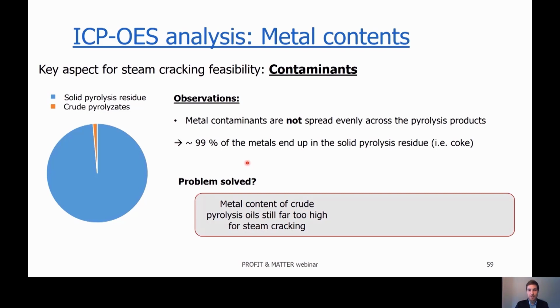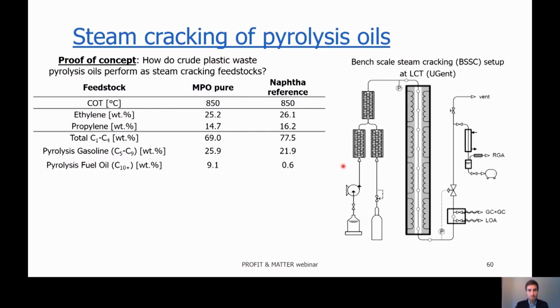This leads to the conclusion that these feedstocks will have massive issues in a steam cracker. This raises the possibility of distillation of the crudes as a further means to reduce the metal contents. For instance, we can remove most of the metals with heavier distillative cuts, while the light cuts needed for steam cracking are then essentially metal free, but this is to be examined in the future.